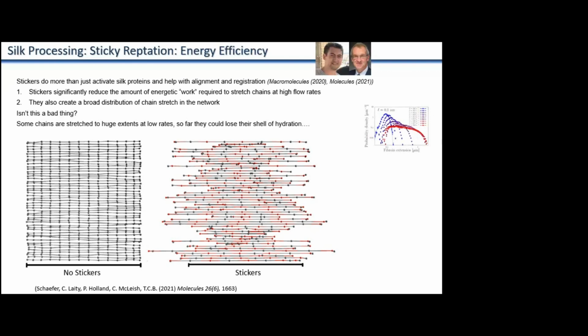Now, I said earlier, wouldn't it be nice if everything was nice and even, nice and consistent? Why would we want this inequity? Why would we want this unusual distribution of stretch in our silk proteins? Well, I mentioned this phase transition. This phase transition is a movement from a liquid into a solid, but it needs nuclei. It needs something to kick it off. And the lovely thing about this, from a polymer flow-induced crystallization perspective, is that these stickers generate nuclei.